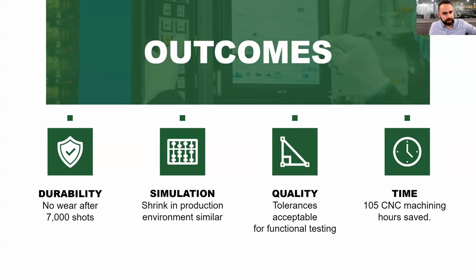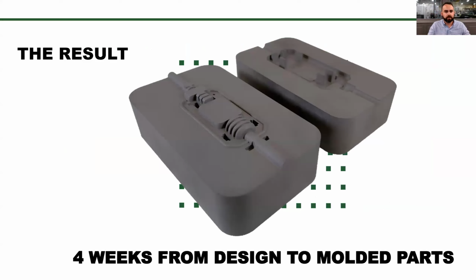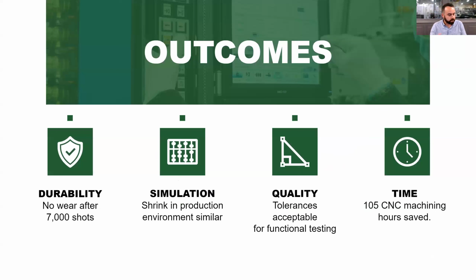Ethan, if you don't mind, can you go back 1 or 2 slides that show the part or printed block? Yeah, so the flat surface that you see towards the back, there was a little window up there. That was the only place that we saw any flash. We had no issues with the swipe by shutoffs or around the perimeter as well, because there was actually a step parting line at the perimeter. So you can see some of the outcomes.